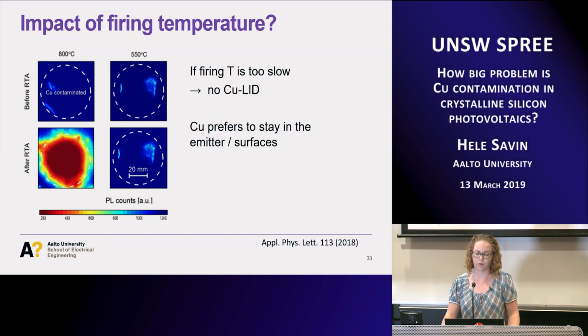The next one is, what about the firing temperature? There are also recent studies on how the firing temperature will impact different LID mechanisms. So we wanted to see this, what happens for copper. Now going down in temperature, we actually see that copper tends to stay in the emitter. So if your firing temperature is low enough, then it really prefers to stay in the emitter and doesn't diffuse to the bulk. This is also something very similar in behavior, let's say, to the LeTID defect, but that has been also studied lately.